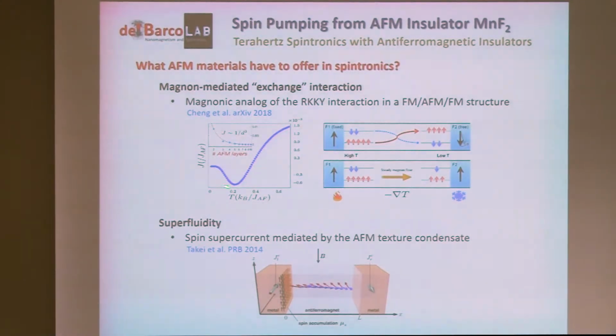But when you look at the evolution with temperature, instead of a monotonic decay that you will get as you increase temperature with the other one, here you have, this is not an oscillatory behavior because it only makes one oscillation if you want, but you can actually change the sign of the interaction between two ferromagnets by changing temperature. This hasn't been demonstrated yet. We're trying to do this. And because of that, you could also realize a magnonic spin valve that would operate with differences in temperature.